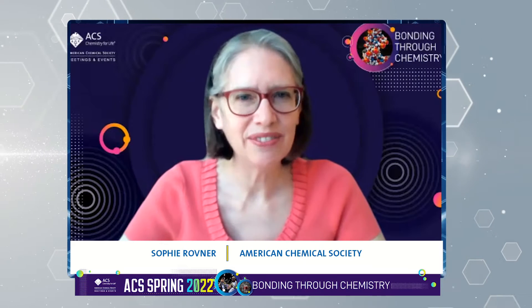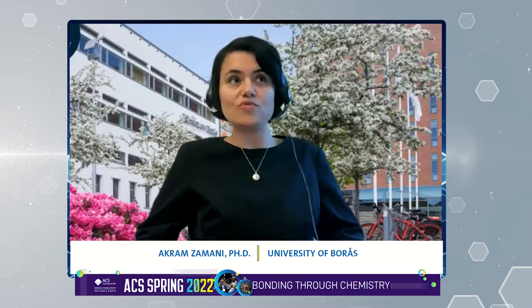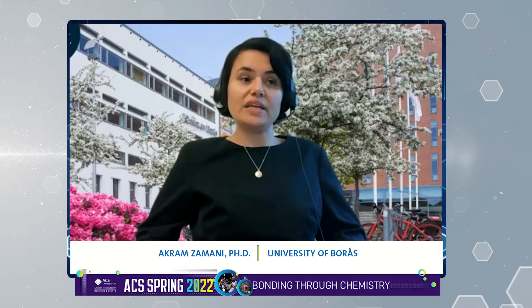All right. So how did you investigate this? We started by cultivating the filamentous fungi on food waste — specifically bread waste, or unsold bread fractions available in supermarkets. We grow the filamentous fungi on bread, then harvest the fungal biomass. Then we tried to create a method to spin yarn from that fungi, and also developed a method to make a leather-like material from fungi grown on food waste.